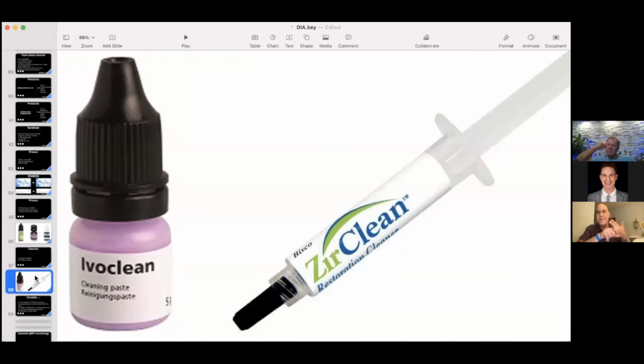You cannot remove that with ultrasonic. You need to use an alkaline solution. These two are very alkaline. You apply it, you let it work 20 seconds, 30 seconds, depending on the instructions, and then you rinse it. Now you remove the saliva-contaminated layer and you have exposed your bonding sites to where you had them before you tried it in. And then you can apply your primer. Now your primer has the MDP somewhere to bond. If you don't do this, you're not going to bond.